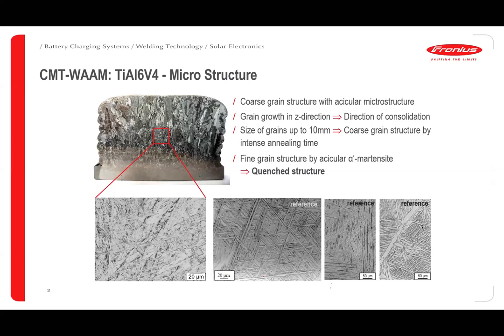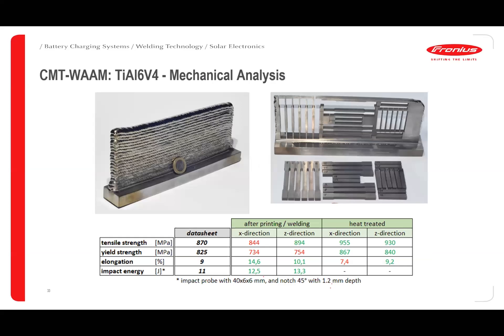Normally, whenever you see structures like this, whoever is working on metals will know that this is going to be some kind of an issue, because the needle-like structures always create some kind of brittleness in the entire structure. But through our experience, when we had a structure like this, where the grain has grown towards the length of the area where the heat gets dissipated, we will be able to see the mechanical analysis that we have done. We have done the wire cut of all these samples, and we have tested with respect to the Charpy and also the impact.